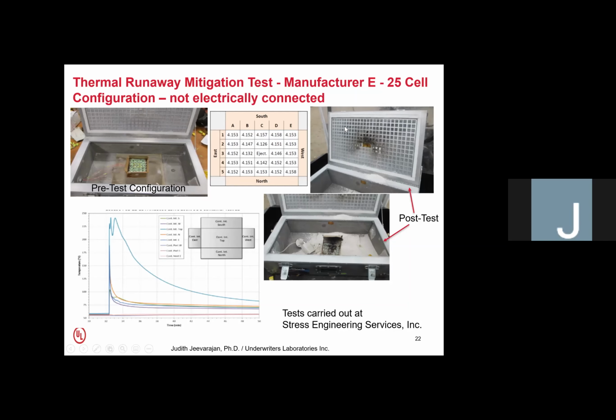But we went with the sacks that had the glass beads on the underside of the lid, and we carried out this test. And as you can see from the values of the open circuit voltage of these fully charged cells, only the cell that was triggered went into thermal runaway, and all the other cells did not go into thermal runaway. As soon as the cell goes into thermal runaway, the bag opens up and the glass beads fall on it and smother the cell that went into thermal runaway and prevent propagation of the thermal runaway.